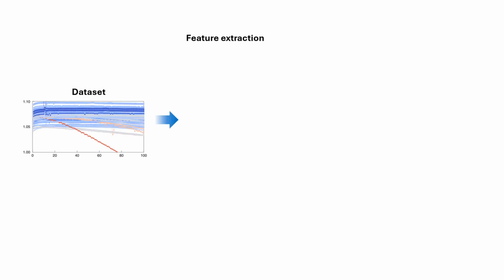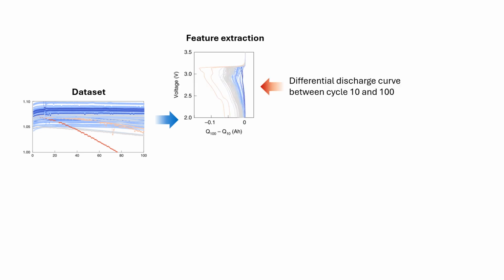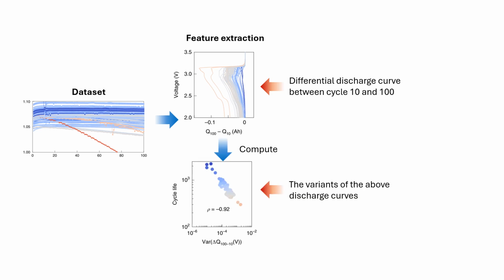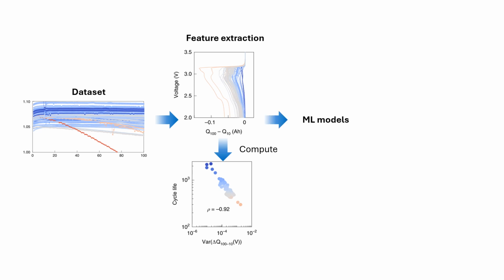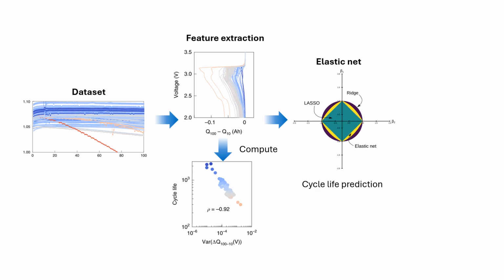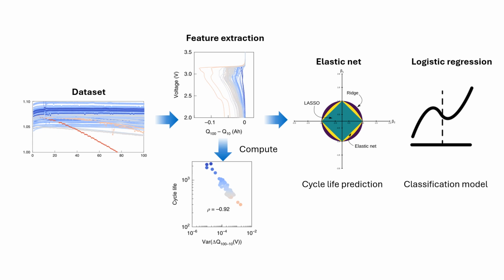The workflow begins with feature extraction, where researchers identified a crucial feature: the differential discharge curve between cycle 10 and cycle 100, and computed its variance. The resulting value showed a strong negative correlation with cycle life, making it a reliable predictor. The next step involved training machine learning models using the selected features, with elastic net used for cycle life prediction and logistic regression for high-low cycle life classification. A key highlight of this work is that strong predictive performance was achieved using rather simple machine learning models.